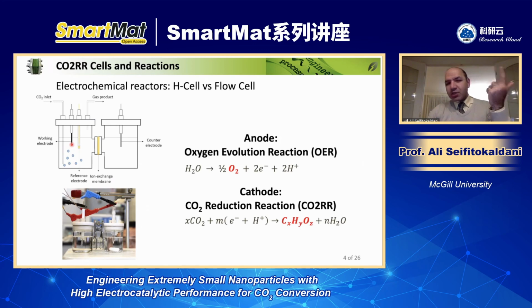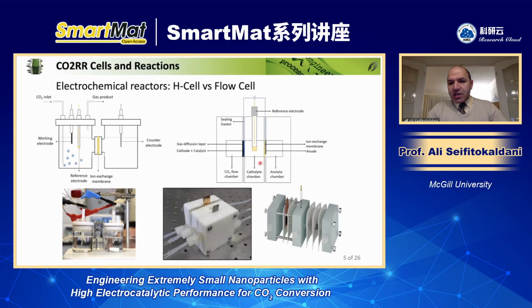First of all, you cannot use any type of electrolyte that you want. For example, if you use alkaline electrolytes such as potassium hydroxide, then the CO2 will react with that. And before being converted to the desired products, it will be converted into carbonate or bicarbonate salts that you don't want. And also, the reaction rate is limited by the diffusion rate of the CO2 from the bulk to the surface of the electrode. So because of these limitations, people started working with the flow cell system, in which we separate the CO2 gas from the electrolyte.